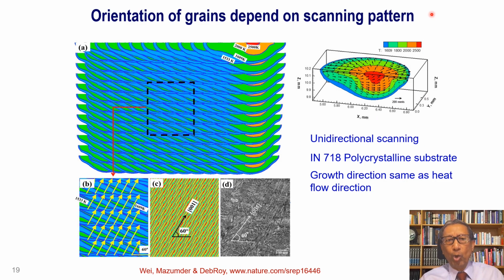Heat transfer and fluid flow models can be very helpful in understanding the evolution of grain structure. This figure shows unidirectional scanning of a laser beam from left to right. So the melt pool looks like this. The isotherms are compressed ahead of the beam and expanded behind the beam near the trailing edge. The primary heat flow direction is perpendicular to the surface of the fusion zone. This is also the direction of the growth of the primary dendrites. So the primary dendrites grow at an angle that is about 60 degrees with the scanning direction, and that is what we see in the calculations as well as in the experimental results.